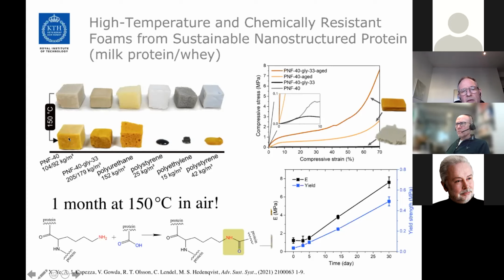So these are two proteins, one with a plasticizer and one without. Of course, at 150, you will have a loss of plasticizer. But what we realized was that this material improves its properties through this 1 month period. You can see the modulus and strength of the material as a function of time. That's because the proteins form isopeptide bonds, as you see an example down here. So not only does it get stronger and stiffer, but it also becomes tolerant to normal solvents that you usually can dissolve this material in. So we're actually achieving a better and better material the longer we treat it at these high temperature conditions. This is something we will pursue further.